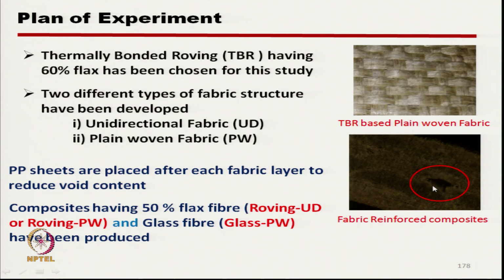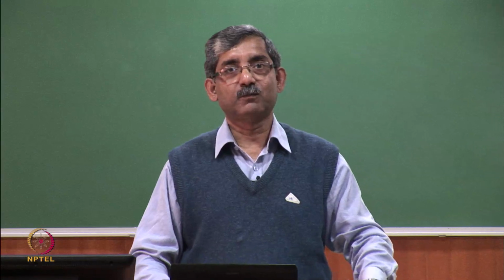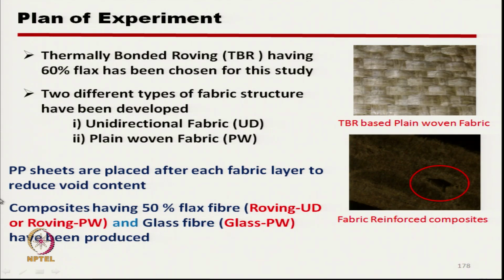We have observed for a few fabrics, in some specific zones, voids or improper melting due to a composite making problem, and we have eliminated all those samples. PP sheets are placed after each fabric layer to reduce the void content. We found that if we do not use a PP sheet after each layer, the void content increases. The composite ultimately has 50% flax, in roving UD or roving plain woven form, and glass plain woven fabric composites are also produced.